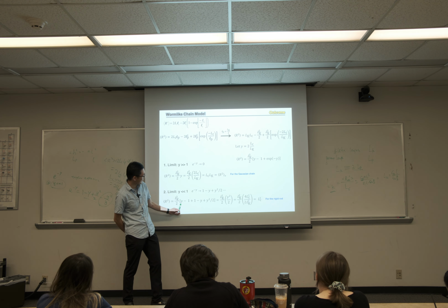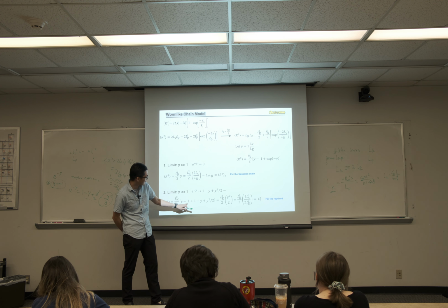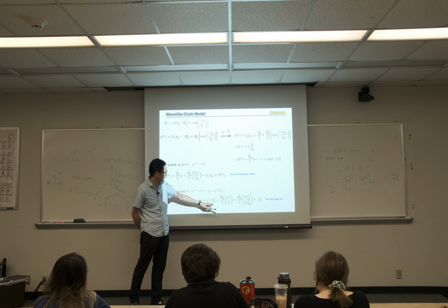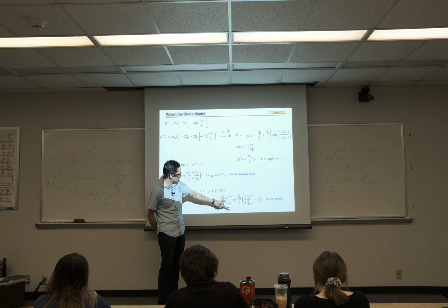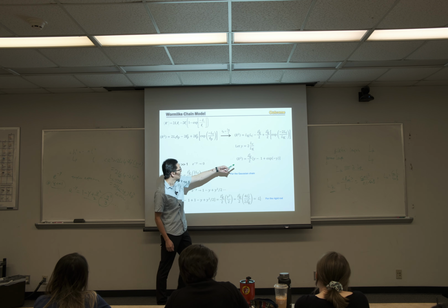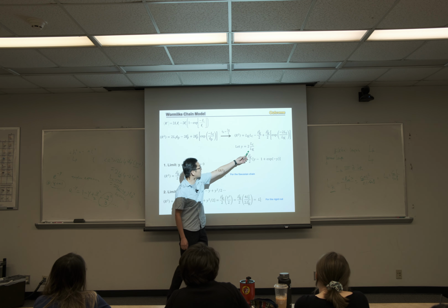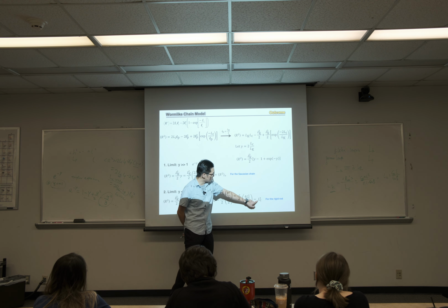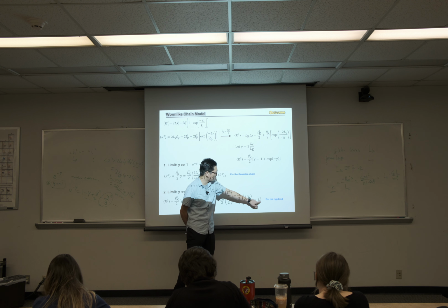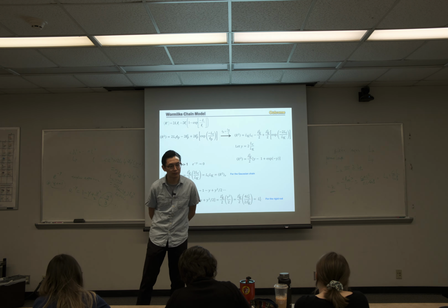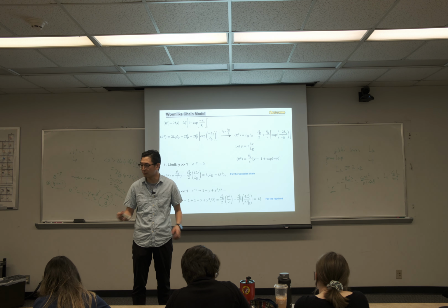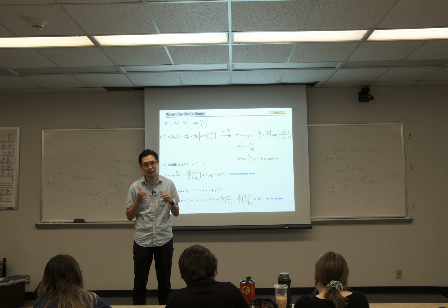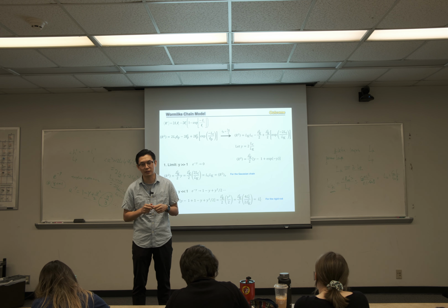If we expand, y minus y cancels out, minus 1 plus 1 cancels out. We are basically left with y squared divided by 2, and we define y as 2LC divided by LK. If you add it here, you will reach the conclusion that the end-to-end distance squared equals the contour length squared. And that makes total sense, right? For a rod, your end-to-end distance is basically the contour length, so your end-to-end distance squared will be contour length squared.